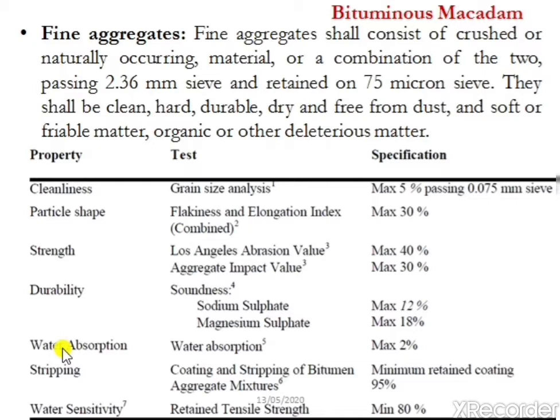The next test on aggregate is the water absorption test. Here, the aggregates are weighed in their dry condition, and let us consider that weight as W1. After weighing, the aggregates are kept in water for 24 hours. After 24 hours, the aggregates are removed from the water and kept at atmospheric temperature for half an hour. Then the aggregates are weighed, and let the wet weight of the aggregates be W2. By using W1, the dry weight, and W2, the wet weight, we can calculate the percentage of water absorbed by the aggregates. If the percentage of water absorbed by the aggregate is more than 2%, then the aggregates can't be used in the construction of the pavements.